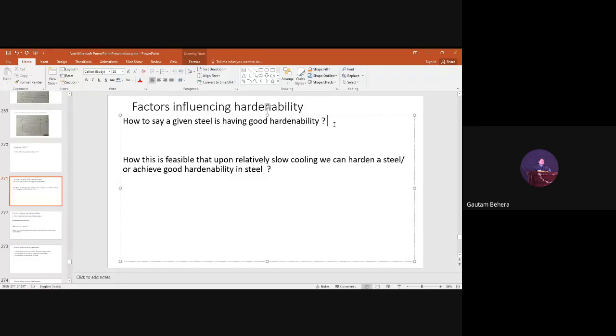Suppose the steel is somewhat thicker, of higher dimension, the thickness is very high. In that condition, obviously the cooling rate will not be the same everywhere. The cooling rate will be faster at the surface, but at the center it will be slower. Because the cooling rate also influences the decomposition of austenite to martensite, or the decomposition of austenite to pearlite. One is the transformation temperature, and the cooling rate also affects what kind of transformation product you will get, whether the transformation temperature is higher or lower, and whether your cooling rate is very slow or fast.